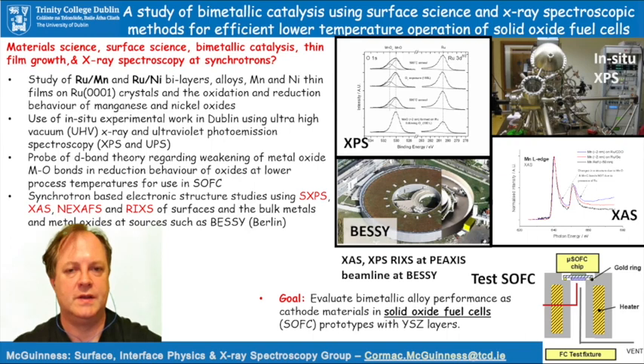This will use in situ ultra-high vacuum chambers in our group in Trinity College Dublin, as well as X-ray and ultraviolet photoemission spectroscopies. What is the underlying theory behind what we're going to study? It's a study of d-band theory regarding how catalysis such as that induced by ruthenium can weaken metal-oxygen bonds and affect the reduction behavior of oxides, such that these are reduced at lower process temperatures, such as might be useful for solid oxide fuel cells.